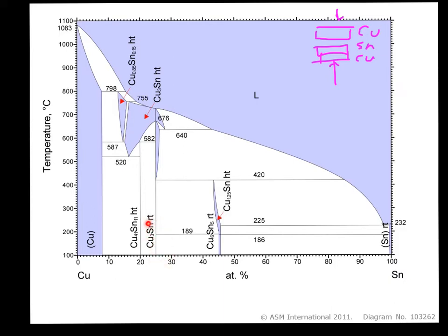and that basically exists there. And then you can end up with a relatively stable material, if you're over here somewhere, where the tin has been incorporated into the copper at a relatively low temperature, even though it's a high temperature for tin, and you end up with phases which now have a very high melting temperature, right? So you've gone from a low melting temperature component over to these phases here, which have a relatively high melting temperature. So this is one way to exploit our knowledge of the equilibrium state of a system to design something that we want.